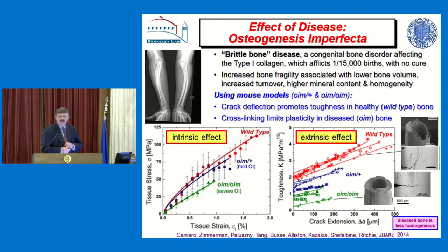Just quickly, there's another mechanism. I've looked at a lot of diseases, but this one is osteogenesis imperfecta. It's brittle bone disease, which children have. And there you get a lot of degradation in the toughness of the bone, and you get a lot of mineral formed all over the bone structure. So if we look at tensile tests, these are stress-strain curves. Wild type is healthy bone, and these are the bones from mild and severe osteogenesis imperfecta, and you can see that the strength drops dramatically, and the ductility, the strain it can tolerate, drops dramatically, and that's due to this increased cross-linking, so the bone can't slide.